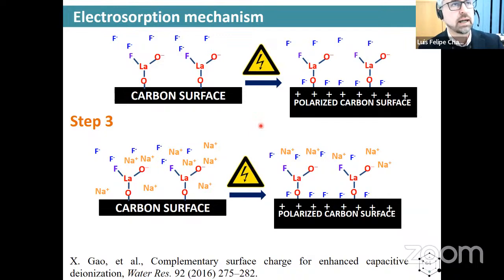I mean, higher values of potential of zero charge, higher values of overpotential. No, these values are higher than the potential of zero charge. Means that you have more attraction for the anion towards the surface, as you can see here. So then this positive charge can be located on the surface of the carbon material. No?